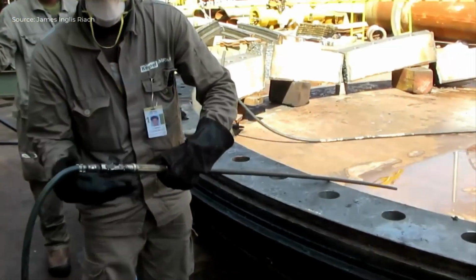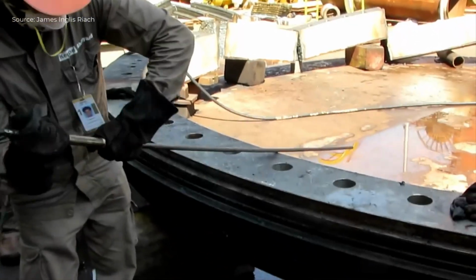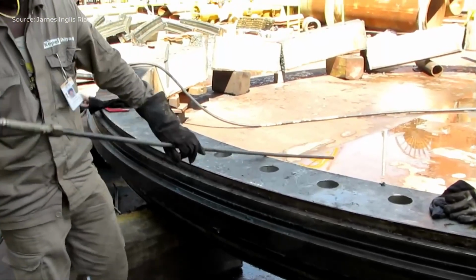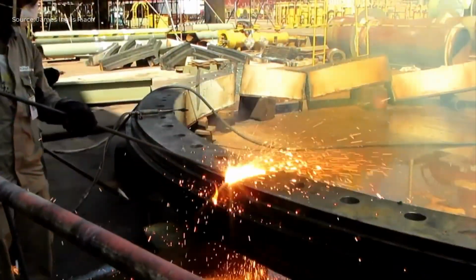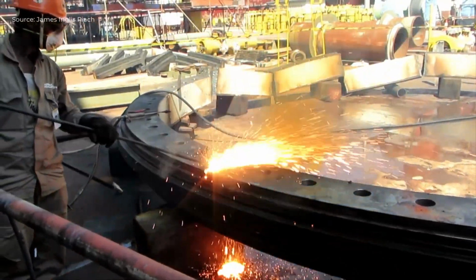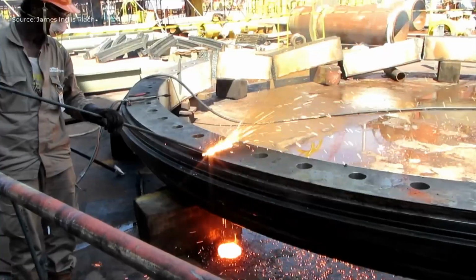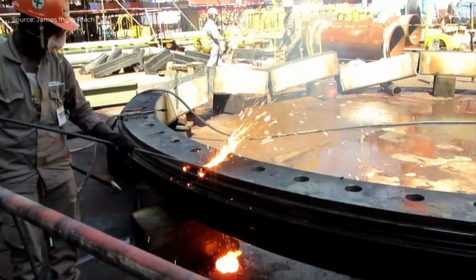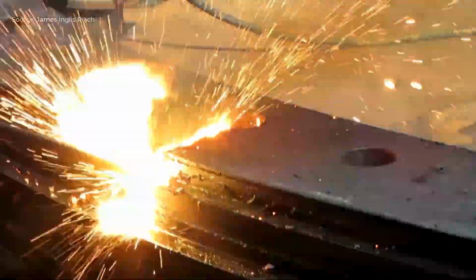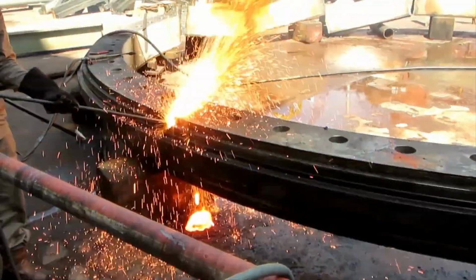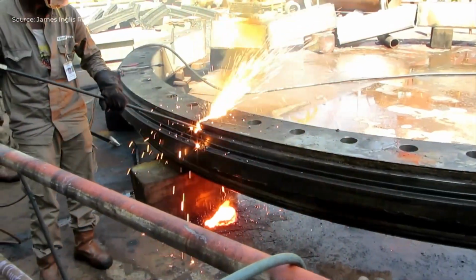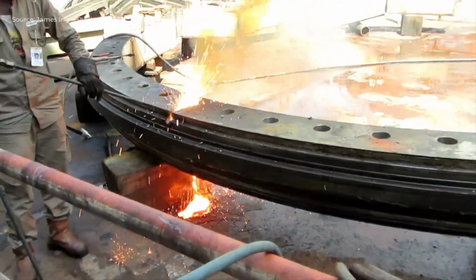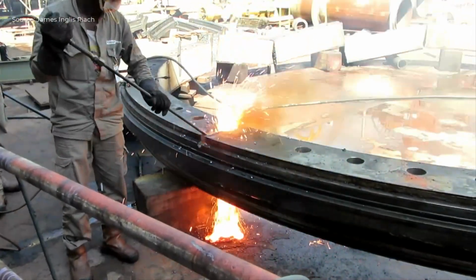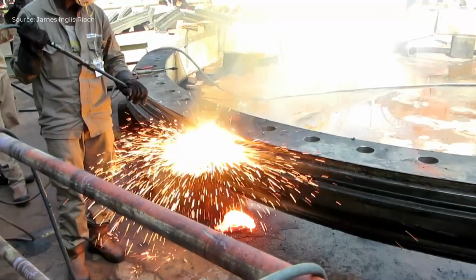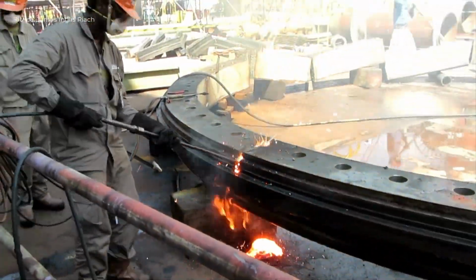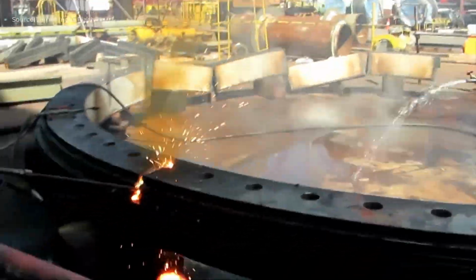The turret bearing was cut with a heat cutter, due to excessive clearance and lack of warranty from the supplier. The bearing, made of carbon steel with heat-treated rollers and an inconel coating, was too large for conventional cutting. A heat cutter, consisting of iron rods inside a conduit with an oxygen flow, was ignited with an oxyacetylene torch. After ignition, the cutter burned at a temperature of approximately 4,000 degrees Celsius, melting the hard materials of the bearing.